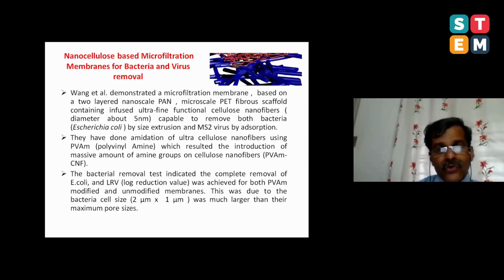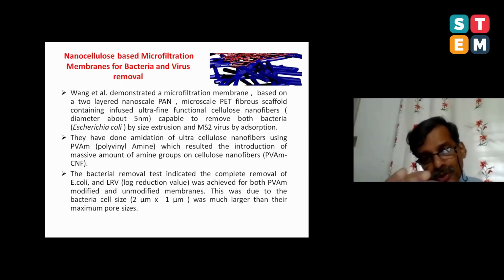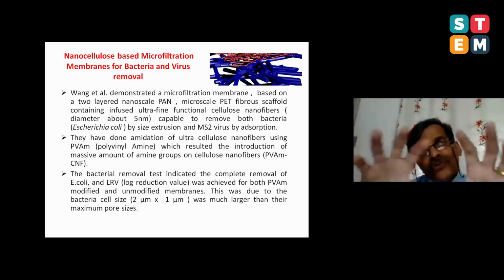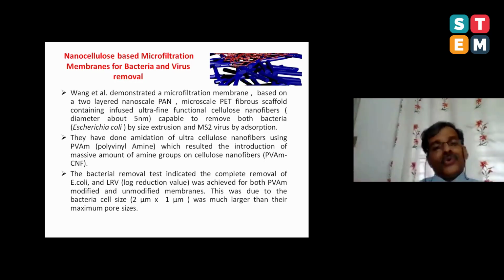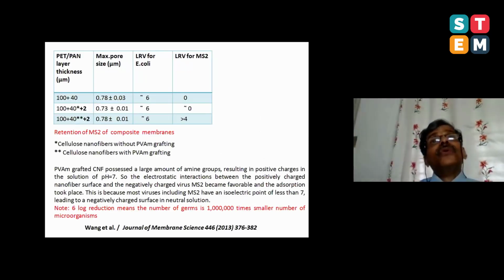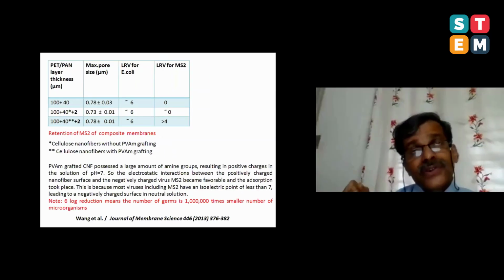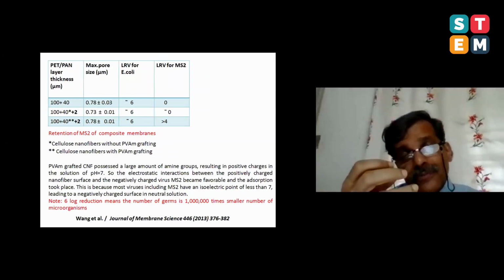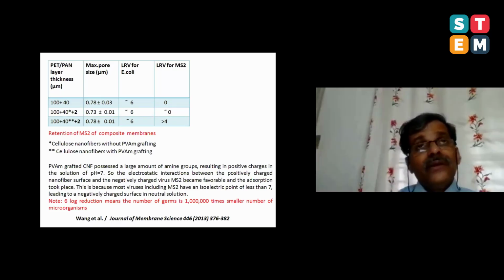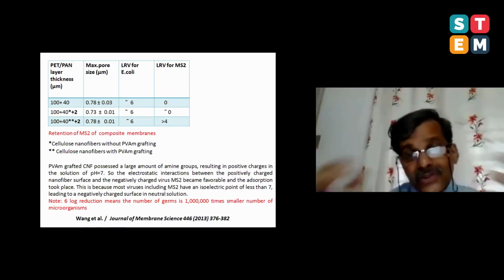The best chemical treatment for virus removal is to modify the nanocellulose and put on amino groups. Look at this filter. The bottom side is made of PET and the top one is coated with nanocellulose. If you modify with polyvinylamine, then you can put positive charge on the surface of nanocellulose, and it can trap all the viruses, because viruses have a lipid coating which is negatively charged. If the nanocellulose surface is made positive, all the viruses could be caught by electrostatic interactions. Bacteria are bigger in size, so you can remove them by the size exclusion principle.